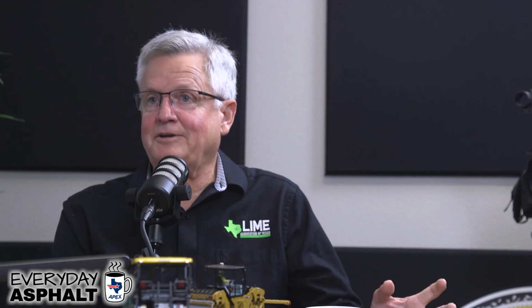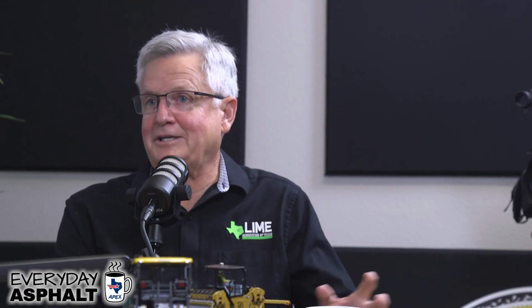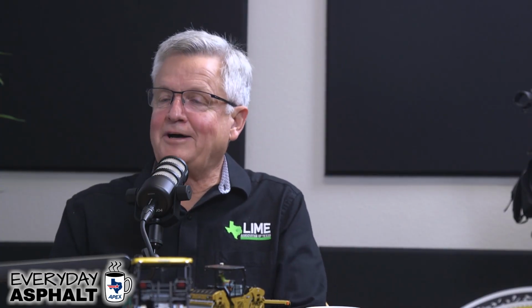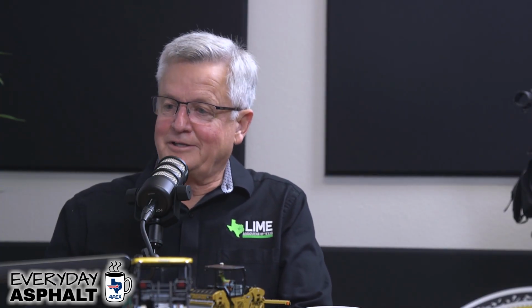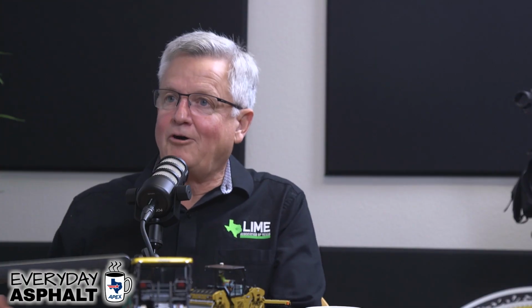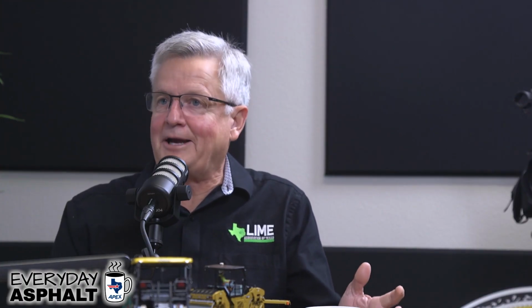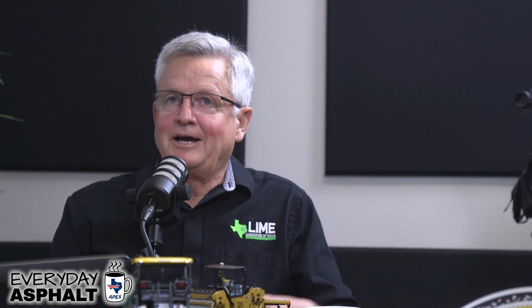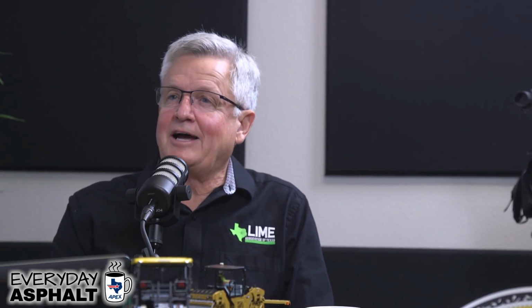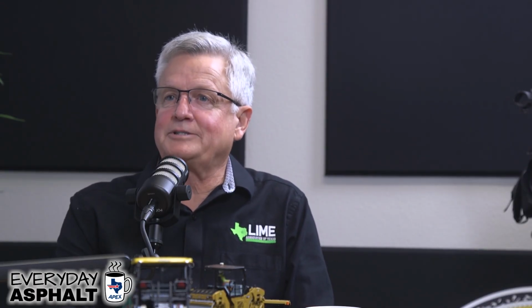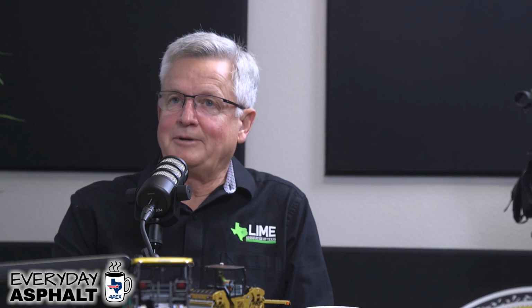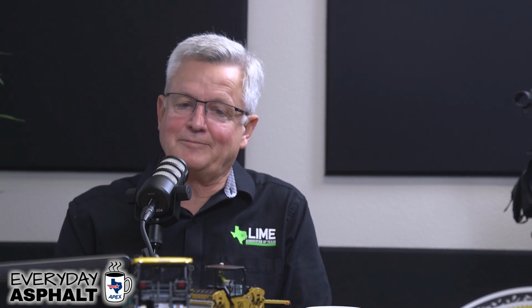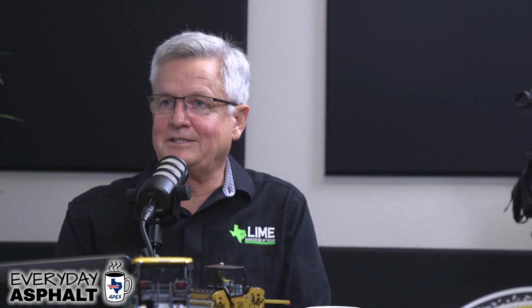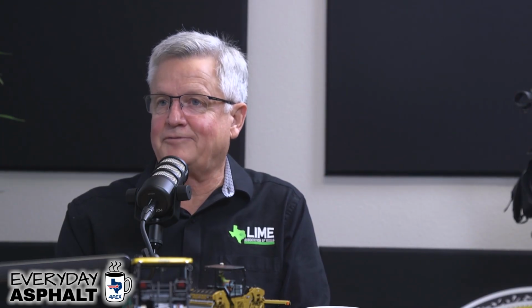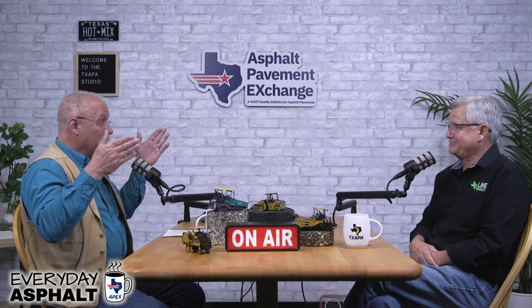part of my job in the flexible pavement section was to do forensic studies. And so it was very frustrating to go out and find all these jobs that had rutting or stripping, and they all passed the initial specification. Going back to the Marshall stability, it didn't identify a lot of projects that had mixes subject to rutting. And the same thing with the Hveem test. It just didn't screen out the bad actors very well. This test had a lot of variability. Yeah, a lot of variability.